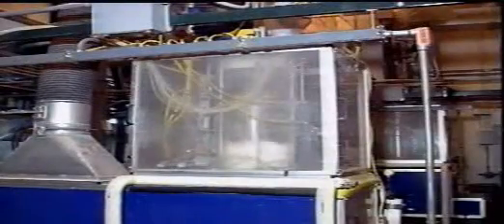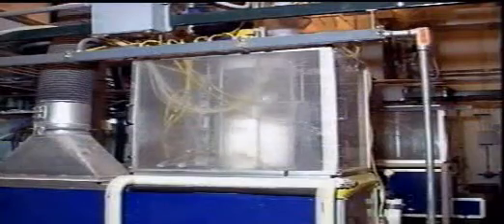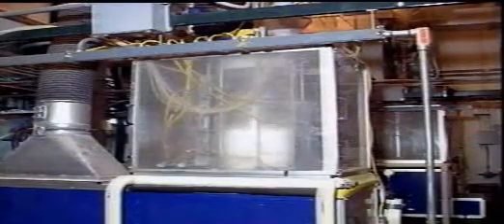The process begins with polymer beads being pre-expanded by steam to a lower density for molding. This special batch-type pre-expander uses a measured weight of beads and expands it to a set volume to assure exact density. After a short stabilization period, the beads are injected into machined and polished aluminum tooling and steamed again to fuse them into a very accurate foam in the shape of a part of the finished casting.